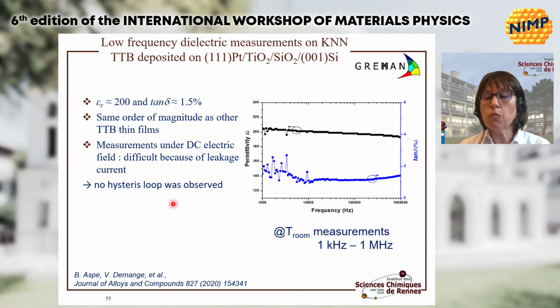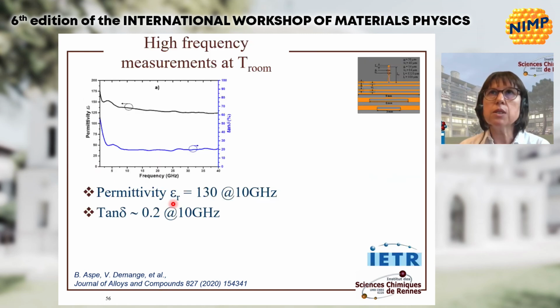No hysteresis loop was observed, probably because of the leakage current. At high frequency with a coplanar device, the permittivity has been measured to be around 130, with more or less no dispersion between 5 and 40 gigahertz. And the losses are typically about 0.2 at 10 gigahertz.